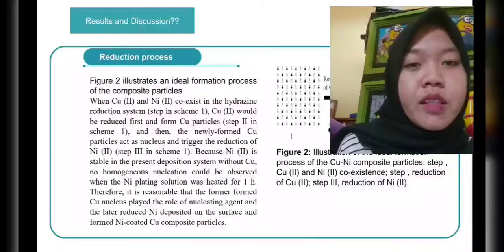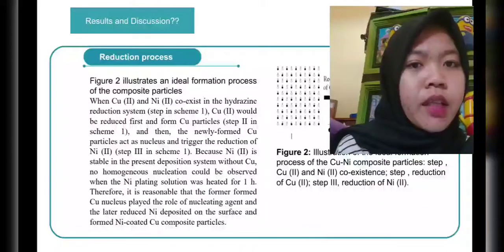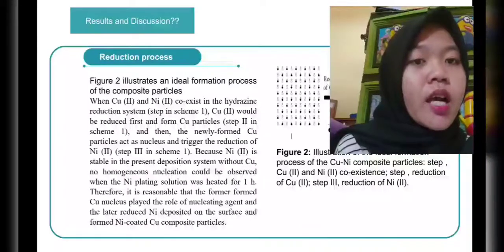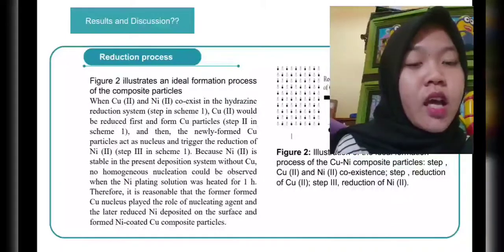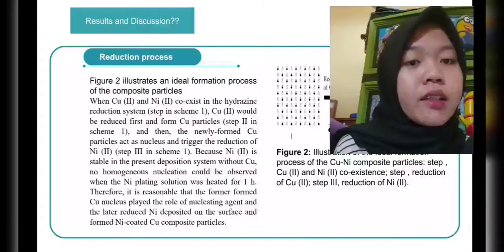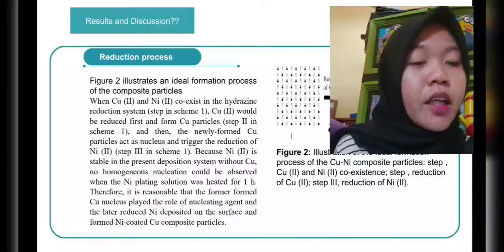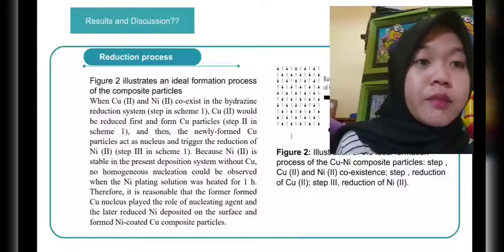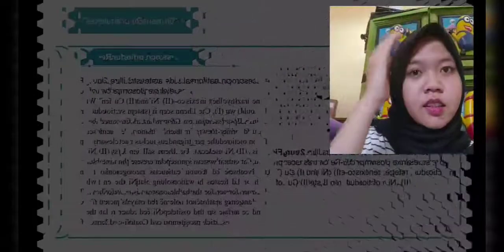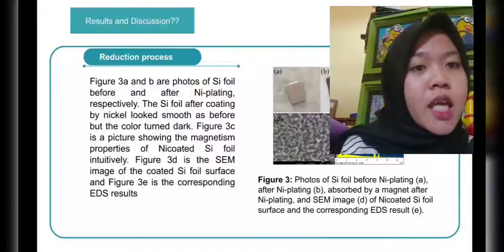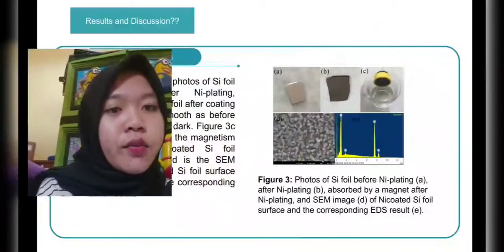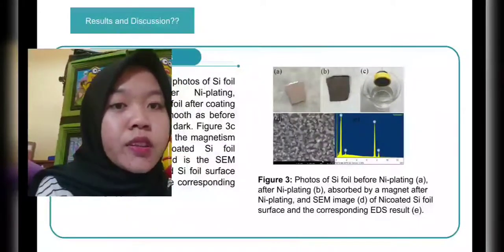nickel 2. Step 3 in scheme 1, because nickel 2 is stable in the present deposition system without copper, no homogeneous nucleation could be observed when the nickel plating solution was heated for 1 hour. Therefore, it is reasonable that the formerly formed copper nucleus played the role of nucleating agent, and the latter reduced nickel deposit on the surface and formed nickel coated copper composite particles. Figure 3. You can see figure 3 on my PPT.